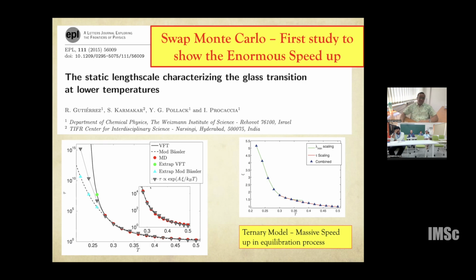And I'm saying the estimated time scale because this is the place where you do not have an idea about what the relaxation time should be. If you fit your high temperature data up to these areas via various forms, the lower estimate turns out to be at least 10 to the 10, which is at least a many-fold speed up in the dynamics. And using that, we looked at various dynamical and static properties, particularly computed the static correlation